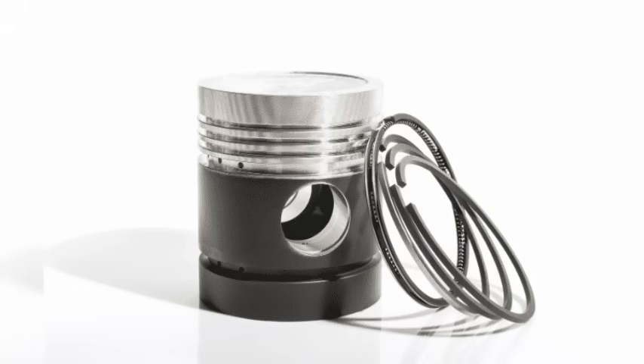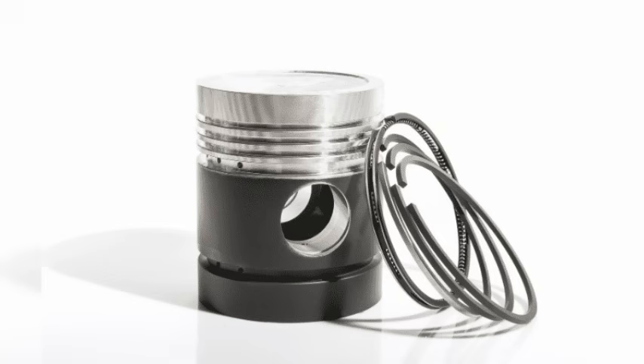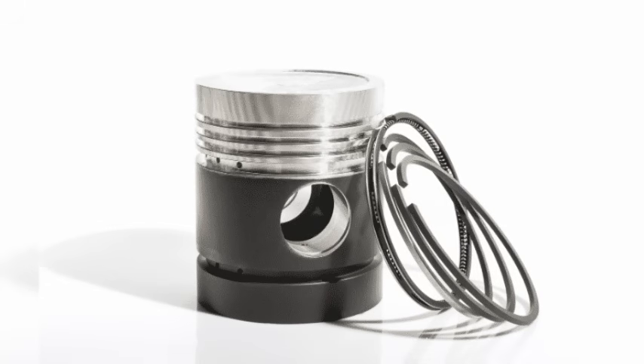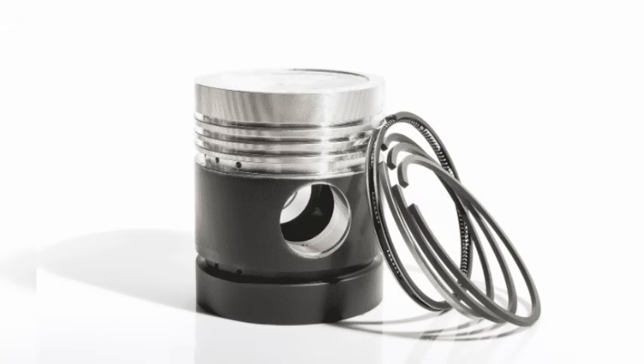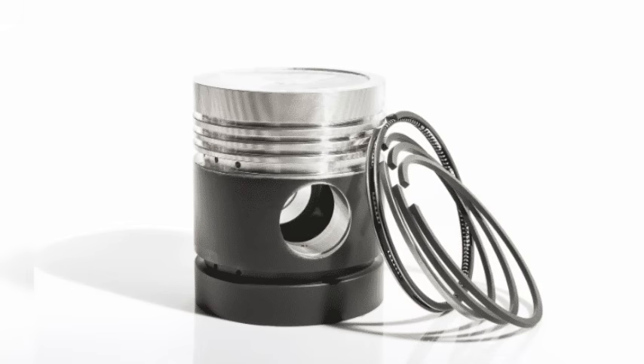Challenge 3. Porosity. Thick chrome plating tended to develop microscopic cracks and pores during the plating process. In decorative applications, this didn't matter. In an engine, these pores could retain oil, actually beneficial for lubrication, or potentially lead to accelerated wear if they propagated. Hastings found that controlled porosity was actually advantageous. Microscopic pores in the chrome surface retained oil, improving lubrication. This became a feature, not a bug. Later, they would deliberately create controlled porosity through specific plating techniques.